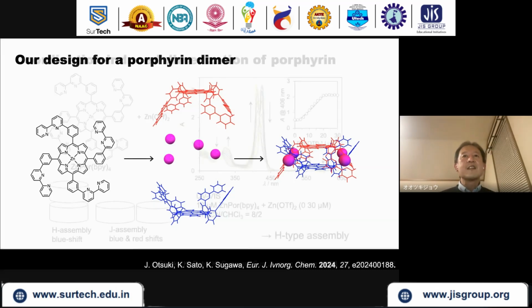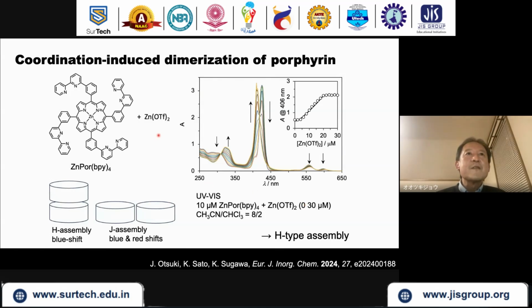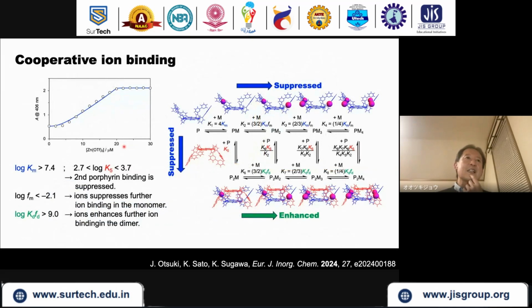So this was our intention, and indeed we have shown that upon addition of zinc ion here, the absorption spectrum shows a very nice blue shift from here to here, indicating that these electron-rich porphyrin systems are arranged in a face-to-face manner like this one. What is interesting is that the dependence on zinc ion concentration is not a simple binding curve, but shows a pronounced S-shaped curve. This indicates that the binding process is very synergistic or cooperative: at lower ion concentrations, the binding is weaker, but after some ion concentration, binding is stronger.